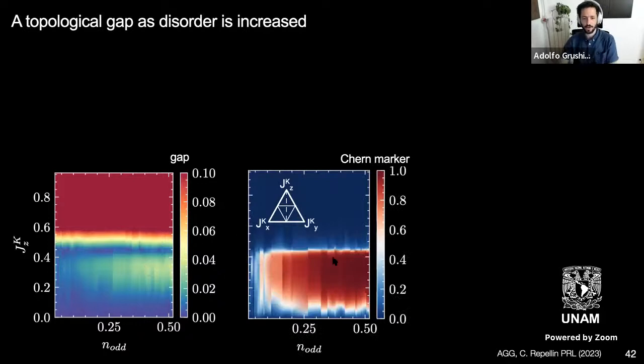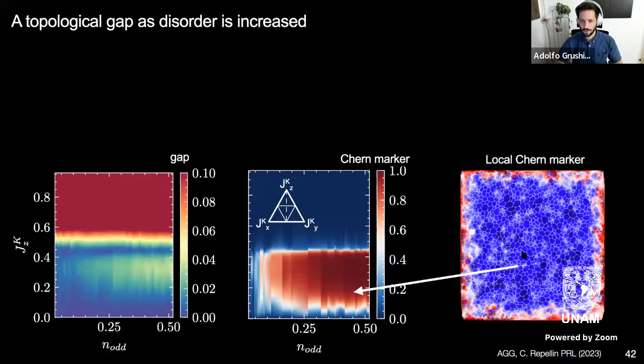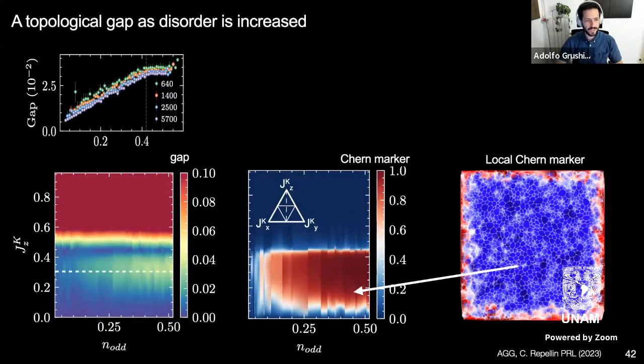And if you calculate the Chern marker, or the average of the Chern marker, which is the topological invariant we were calculating before, you'll see that it's 0, meaning trivial, for this phase as we knew, but non-trivial for this other phase. And if you look at the local Chern marker, this is what I'm showing here. If I take a cut around here, you'll see that the gap grows linearly with the density of odd plaquettes, and then saturates.